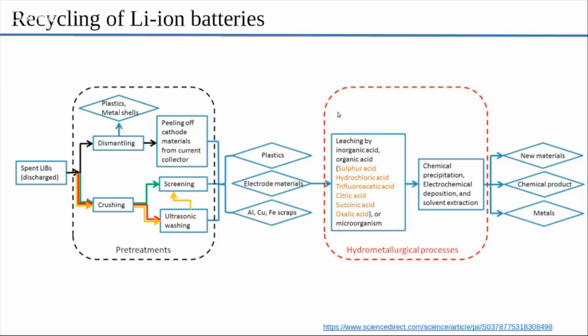Then they're subject to very vigorous hydrometallurgical and pyrometallurgical processes. Hydro means you use very strong acids that can leach the material. Basically, you use sulfuric acid, hydrochloric acid, trifluoroacetic acid, citric acid. You pick the kind of acid that will dissolve only the material you want. It won't affect the other materials. So you pick the kind of acid that is good for, let's say, aluminum or copper or cobalt or nickel. Then you leach that away, and you have a slurry or an acid which contains dissolved nickel or cobalt, aluminum. And then you have pyrometallurgical processes, which further use heat.